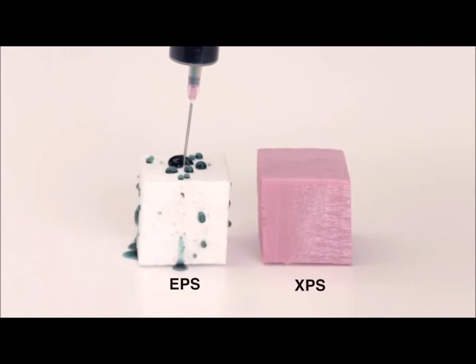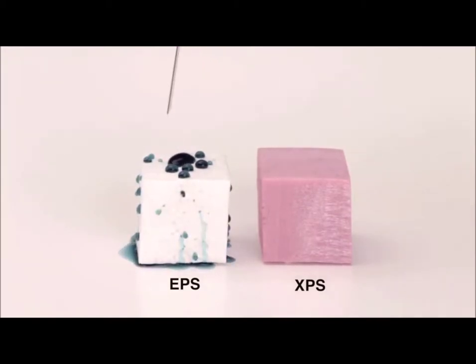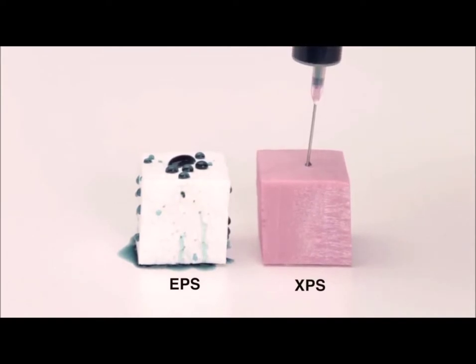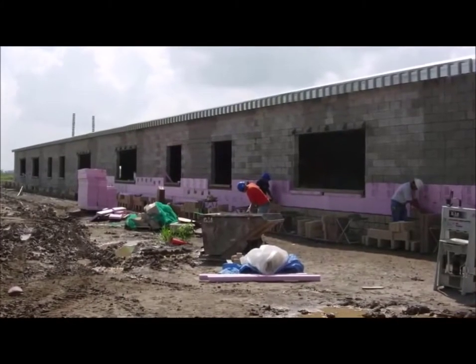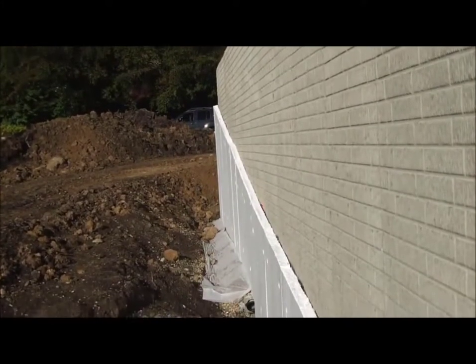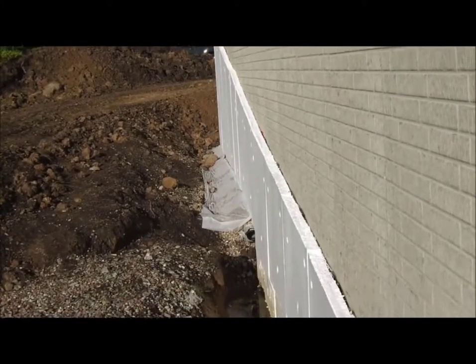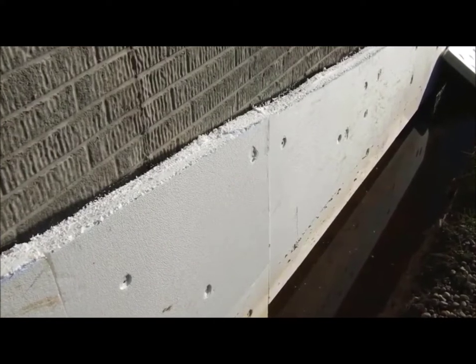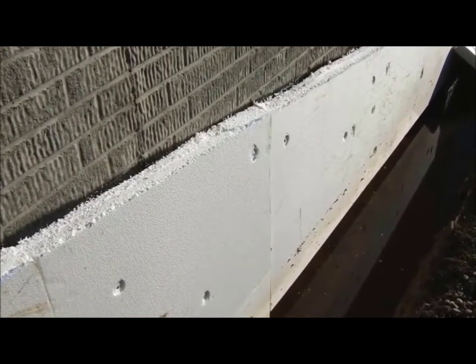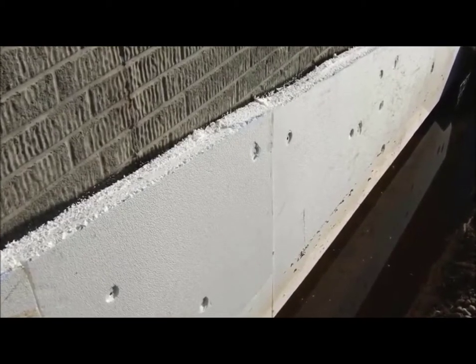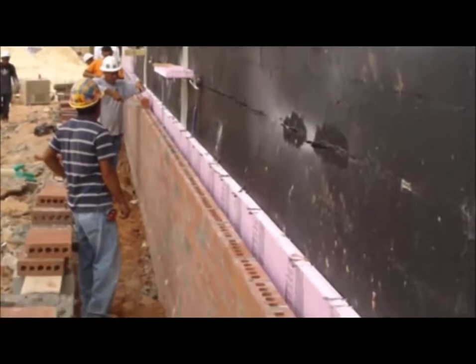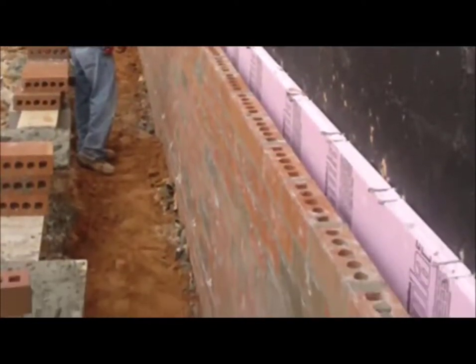ASTM C578 tests are important to measure and quantify the properties of each material. What you see here is a demonstration of how each, Owens Corning's XPS and EPS, handle water, commonly found in a 1-1.5 pound material. In real-world applications, insulation gets wet, but it still must perform. When EPS absorbs water, its R value actually decreases, even when tested at lower temperatures. In fact, EPS exposed to water has a lower R value at 40 degrees Fahrenheit than it does at 75 degrees Fahrenheit. This water absorption also subjects EPS to damage during the freeze-thaw cycle, which can have a negative effect on product integrity. XPS continues to have a higher R value at lower mean temperatures, even when exposed to water.